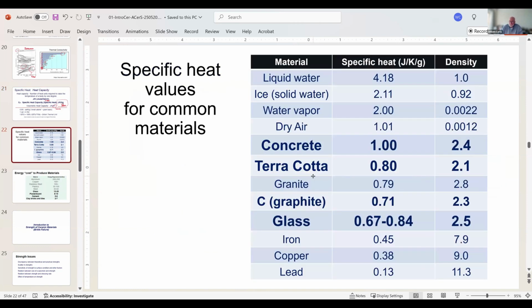So I just have an example of some materials. We're going to ignore water for the moment, okay? So my concretes, terracotta, granite, graphite, and glass are all here, okay? And then they have a heat capacity that's roughly double or maybe even a factor of 7 or 8 times the heat capacity of lead, for example, which is a very, very easy to heat material. Small amount of energy is required to increase the temperature. So lead, copper, iron, iron being an example of, it's almost exactly a factor of 2 before you get to glass, right? I bring water in here for a good reason.